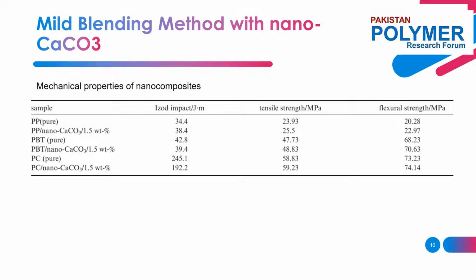The mechanical properties of the nanocomposites are listed in the table. The tensile and flexural properties of the three composites increased with the addition of nano calcium carbonate. However, the impact strength of the polycarbonate and polybutylene terephthalate composites showed a slight drop with the addition of nano calcium carbonate. It can be concluded that the mild blending method is feasible for preparing nanocomposites of both non-polar polymer and inorganic particles, or polar polymer and inorganic particles.